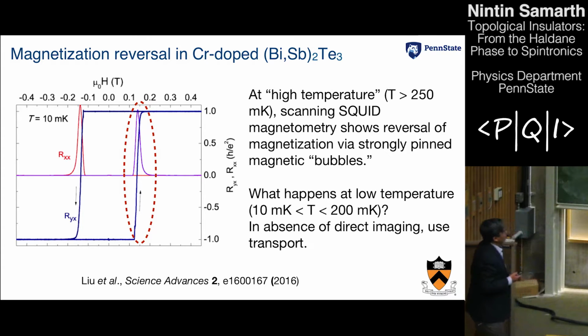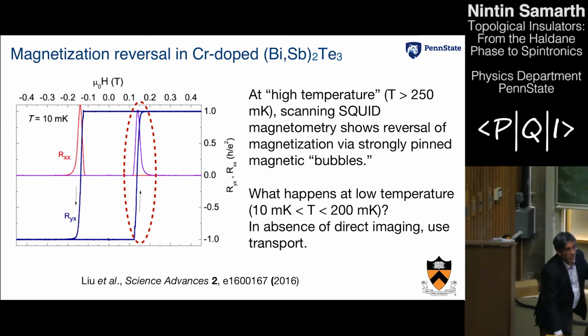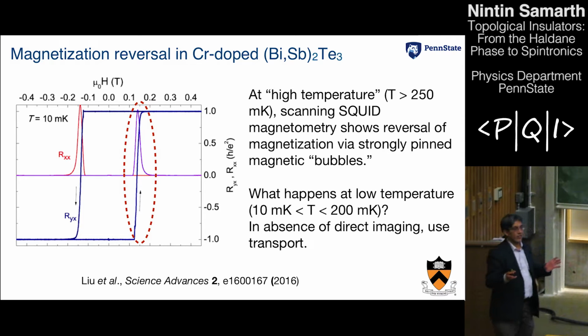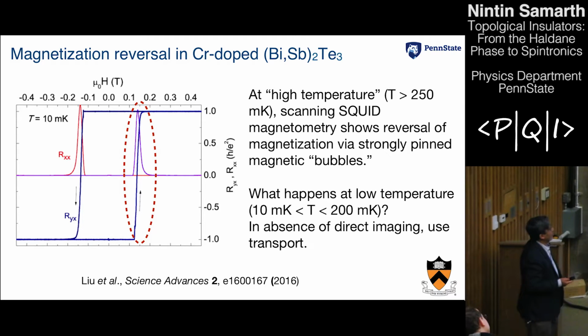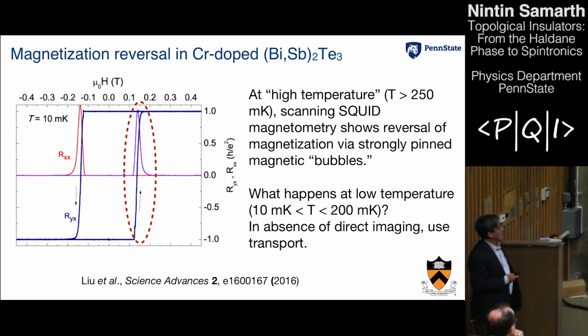Now, one of the questions one might ask is, at these low temperatures of 10 millikelvin, where you get this very precise quantization, how is this magnetization reversal taking place? Is it still dominated by this very local reversal of magnetic bubbles that I showed you, or is it something else? We cannot image at these temperatures in a dilution fridge. We just don't have a technique to do that. And so instead, we decided to see how the magnetization reverses from below 200 millikelvin, looking at this very carefully, simply through transport.